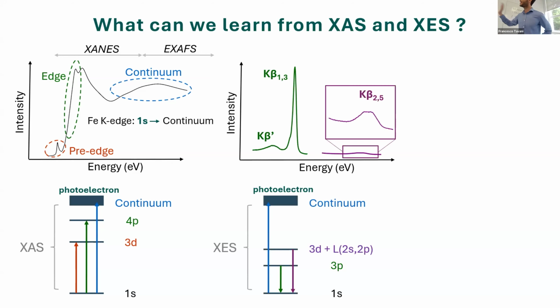If we look at XES, we get a complementary picture of the same process. Here, we are looking at the decay of the excited system. Once we eject the photoelectron, we have X-ray fluorescence transitions, and depending on the energy of these transitions, we can call them K beta prime, K beta 1,3, K beta 2,5. These are complicated nomenclature definitions.